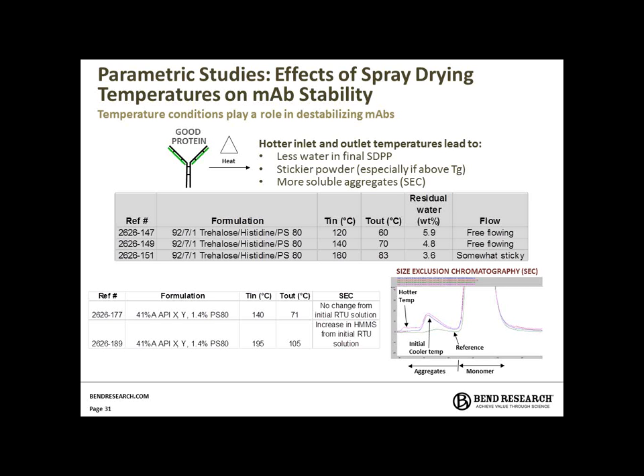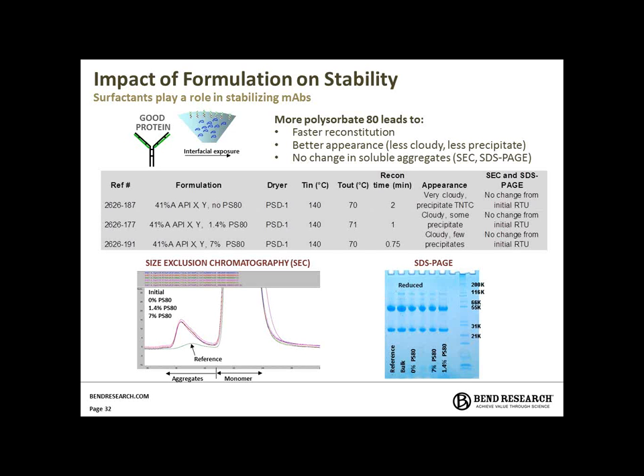We also looked at using SEC for the API integrity of these powders, of the biotherapeutic IgG, using either an initial cooler temperature, a hotter temperature condition, or a modified PSD1. Compared to the reference, we actually decreased the large aggregate formation that was occurring using the hotter temperature conditions that were brought to us. So the process did, in fact, mitigate aggregation as shown by SEC as well as the photograph we saw earlier.